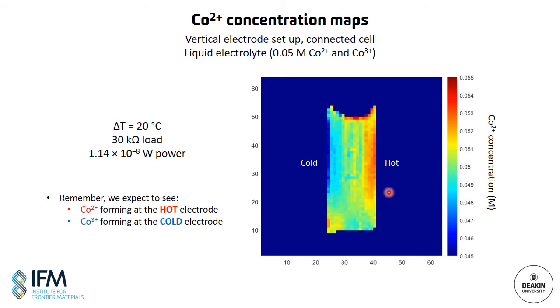you can see a clear concentration gradient in the cobalt 2+, with higher concentrations at the hot electrode as we'd expect, while in the center the concentration is close to 0.05 molar.